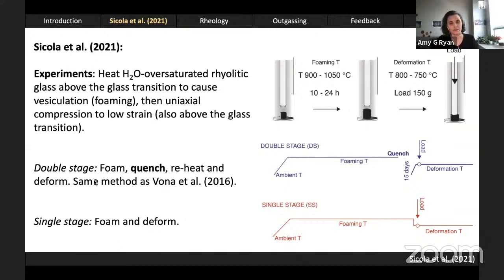The double stage was mimicking a method previously used by Vona et al. 2016. In these double stage experiments, she would heat the core, allow it to foam for some extended period of time, and then rapidly quench it below the glass transition back to room temperature. The material would sit at room temperature and room pressure for 15 days, and then she would reheat it, load it, and deform it. In the single stage experiments, she would do all of these steps in one go. There's no quenching occurring here.